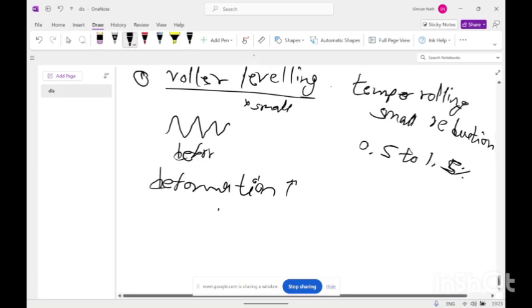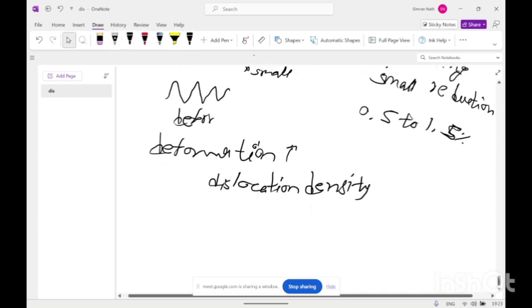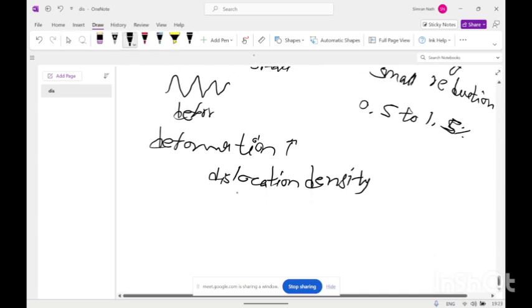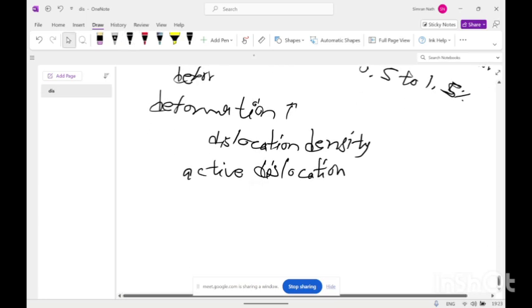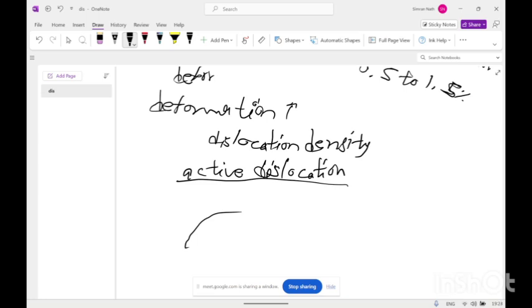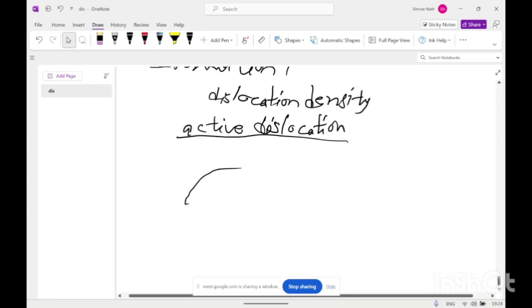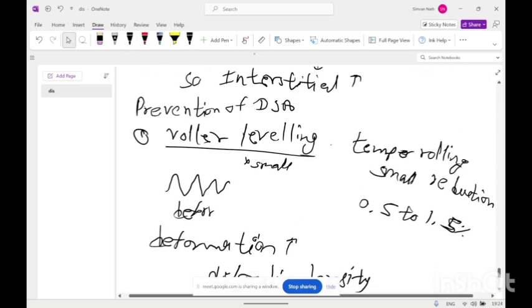As the deformation increases, dislocation density also increases. With more dislocations present, the solute atoms are too few to pin all of them. The active dislocations are higher in number, because the solute atom concentration is limited and they can pin only certain dislocations. The remaining active dislocations can result in deformation while maintaining the stress level. So there will be no increase in stress because of pinning of dislocations by solute atoms. So the serrated flow can be avoided because of roller leveling and temper rolling.